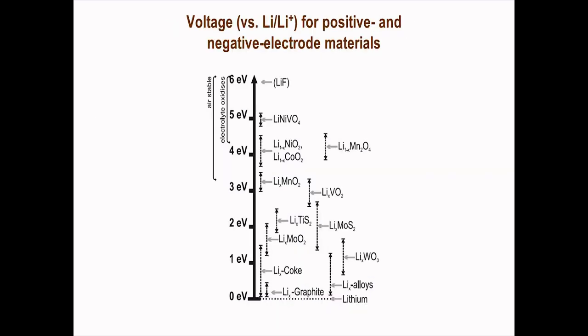If one looks at it a bit more carefully, those materials which form a weaker bond with lithium, like for instance graphite, lithium will stay in the van der Waals space between the graphene layers. When it's a metallic material, lithium will form a metallic bond with the host material. But when one looks at these, which are used as the cathode material, giving a high equilibrium voltage, in these lithium will form an ionic bond, which is a much stronger bond and leads to a much greater voltage.